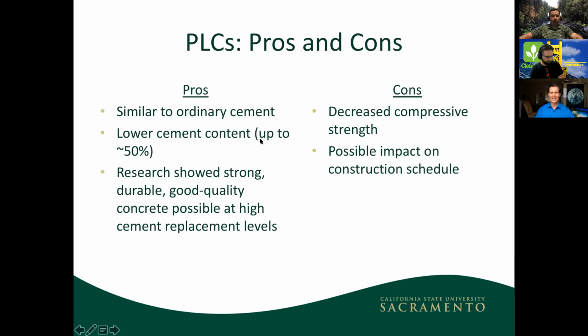Okay, so this is what I was talking about. Our project showed up to 50%. Yes, it's going to decrease the strength a little bit because we have less cement, which is what's providing the strength, but not so significantly that we can't use it anymore. We can still use this concrete, especially in places where we don't require the concrete to be that strong. For example, sidewalks, pavements, slabs for buildings. We don't require concrete that is super strong like we would, for example, in a column of a building. Okay, so we can kind of mix and match and really put the pieces of the puzzle together to use this quality product in the places where it's going to result in lower CO2 emissions. It's going to result in a more environmentally friendly product.